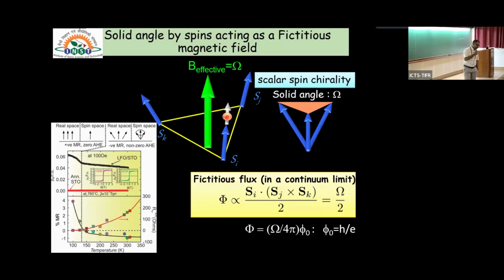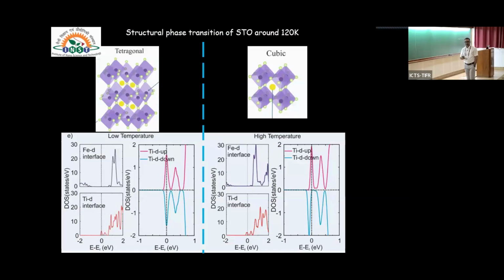Fortunately, the day we got the report, there was a conference at Pune last year and Priya was there. So Priya helped us with a band structure calculation. What it has shown is the following. At high temperature, STO is in a cubic phase, and because of this cubic phase, this system is half metallic in nature. But once there is a transformation from cubic to a tetragonal state, it becomes a non-spin polarized material. So this is a very interesting thing. This is a crystal driven half metallicity to non-half metallicity transformation.